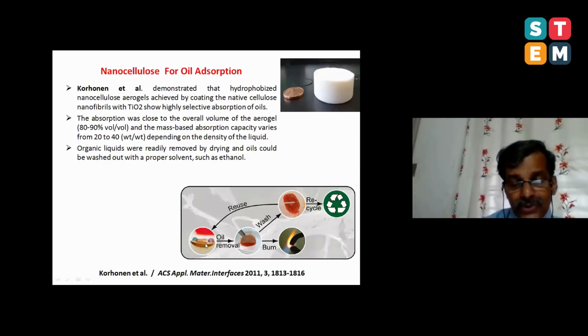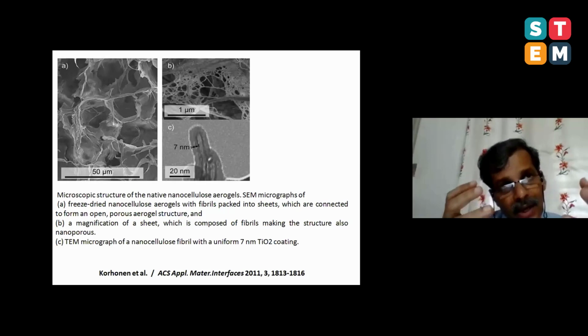This is actually aerogel. Aerogel takes away all the oil because it's hydrophobic. This is a water molecule. Water cannot penetrate because water is hydrophilic. And then you can remove the oil in different ways. You can squeeze out all the oil and reuse it, or you can burn the oil. So this chemically modified aerogel is an efficient material for removal of oil from seawater.